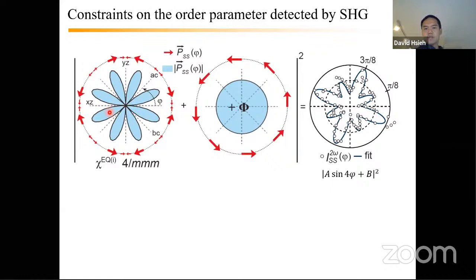And if you fit that just to an isotropic response, some tensor that does not depend on phi, and then coherently add these, you get a pattern that actually fits our data quite well. This gives rise to this big, small lobe amplitude alternation. And that's just because the optical phase is alternating